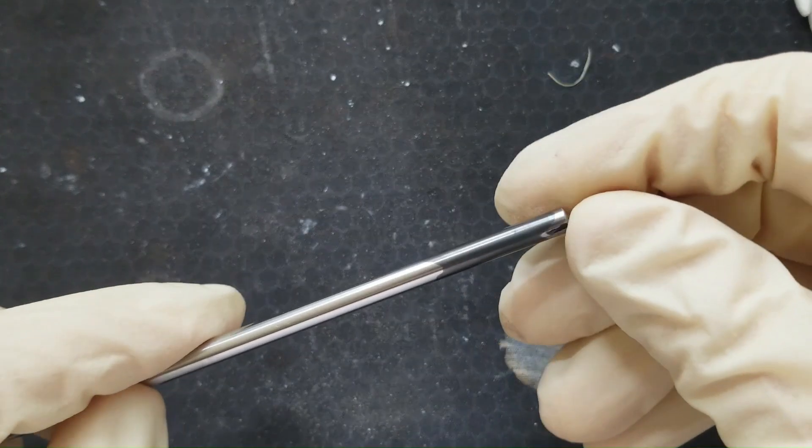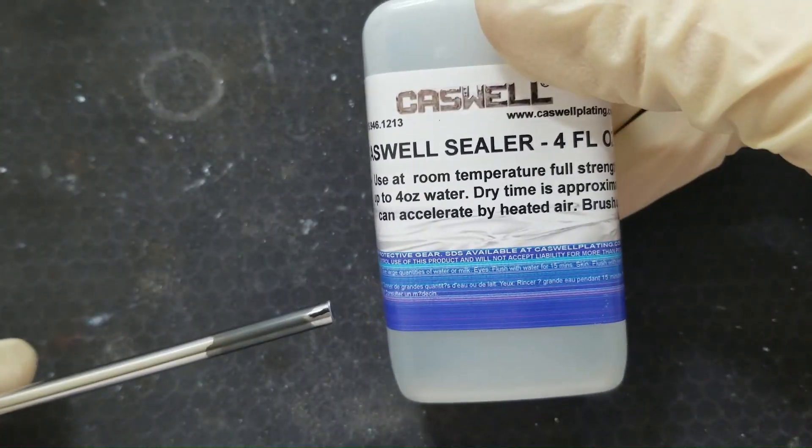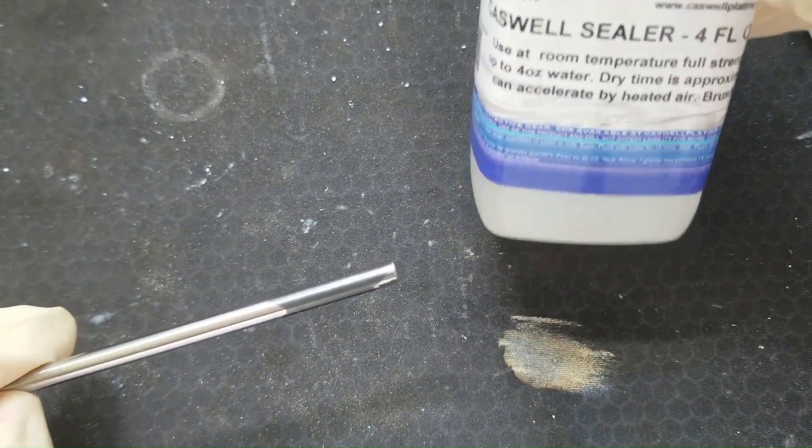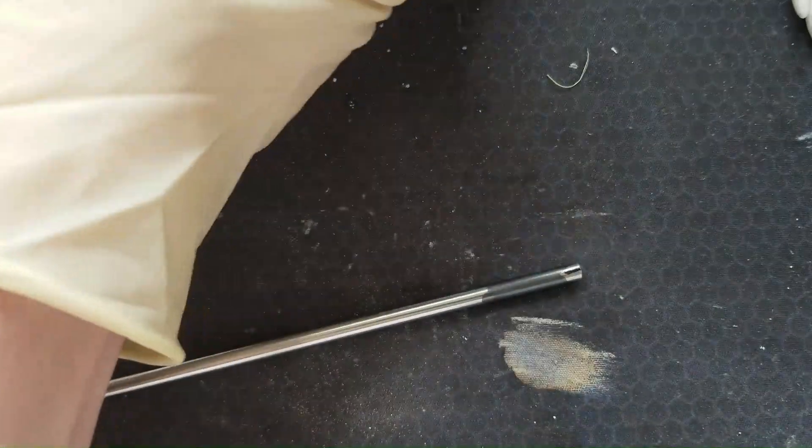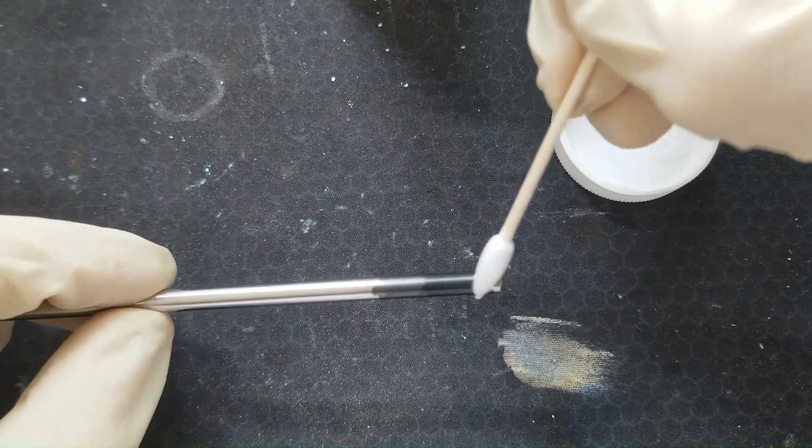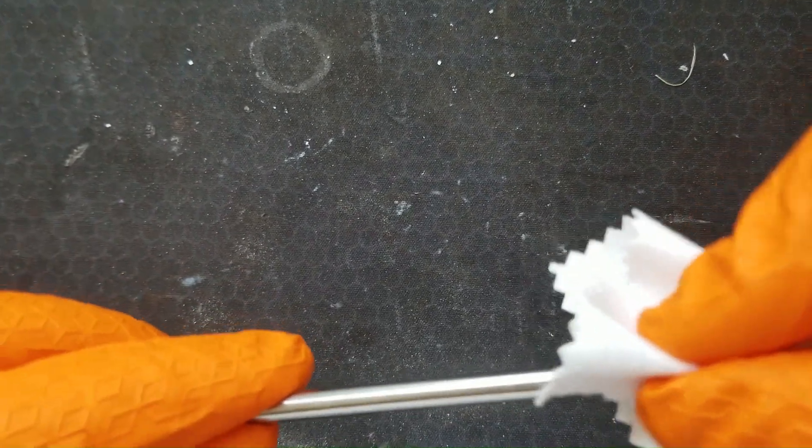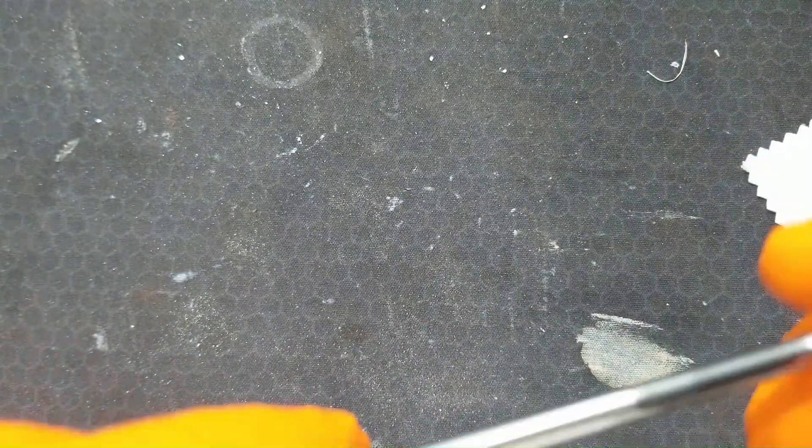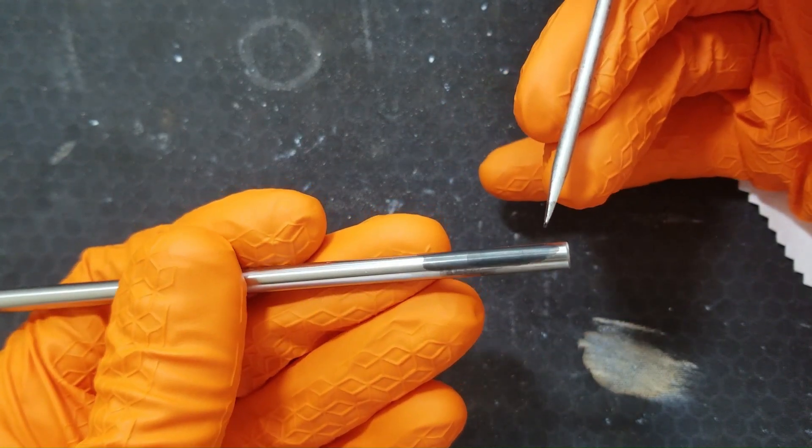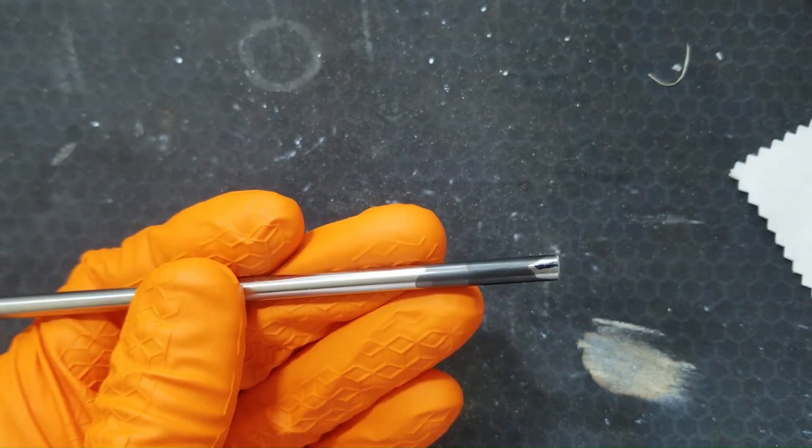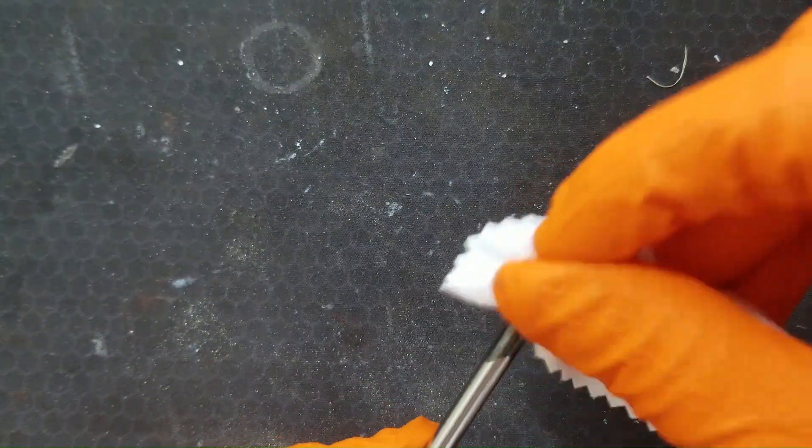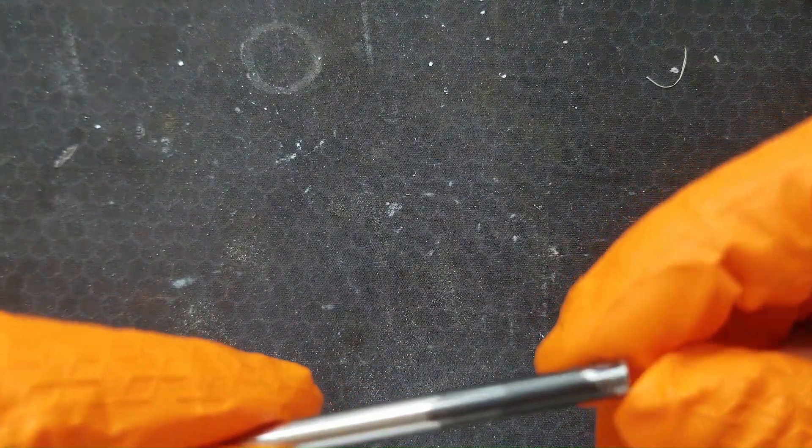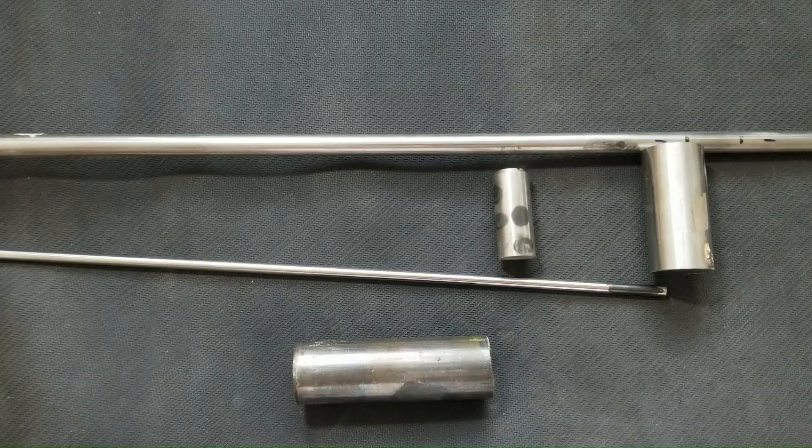So coming back to this 400 series that blackened up really quickly and really nicely, I'm going to treat part of this with the sealer and let it completely dry and then see what the finish looks like and how resistant it is to some polishing action. Let this sealer completely dry. Gave it about 10 minutes. You can see this line right here. There's no sealant. There's the sealant. So it gives it a little bit deeper, darker color. It almost gives it kind of like a waxy finish. This black color looks a lot nicer than that one. This is more black. That's more gray. Pretty pleased with these results.